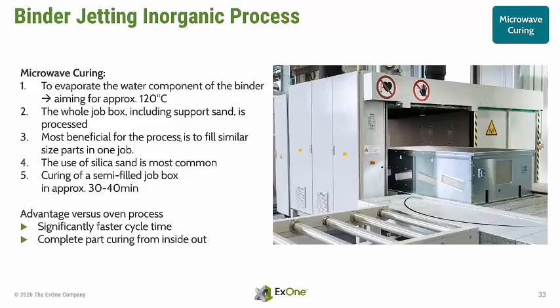This is significantly faster and much more efficient compared to an oven process, as the microwave is curing the cores from inside out. Besides the longer heating cycle, the oven process bears the risk that the outside-in heating introduction would cause water to get trapped if the core boundaries would cure prior to all evaporation of the water that's still inside. This process works very well with silica sand.